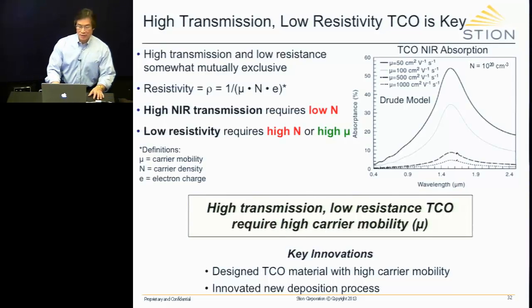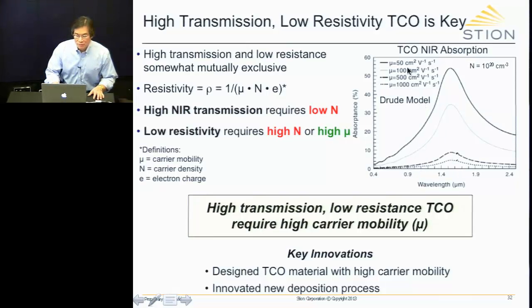Here's a calculation based on the Drude model in which you increase the carrier density. As you increase the carrier density, you can see that the losses get significant. So how do we solve this problem?